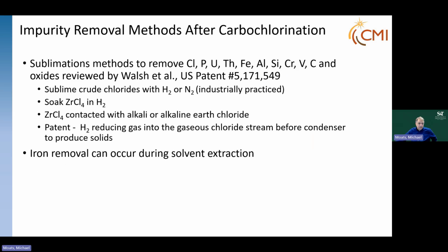To purify the zirconium tetrachloride and the hafnium tetrachloride, there are various patents out there, but basically you sublime them. You heat them up to gases in hydrogen or nitrogen, and that allows some of these impurities to be removed. And I'll show you how to do that. But there are other techniques to do that. Iron can also be removed during the solvent extraction phase. So if you're going to be studying or looking at removing other impurities during this process, then you're going to be looking at sublimation or maybe solvent extraction.